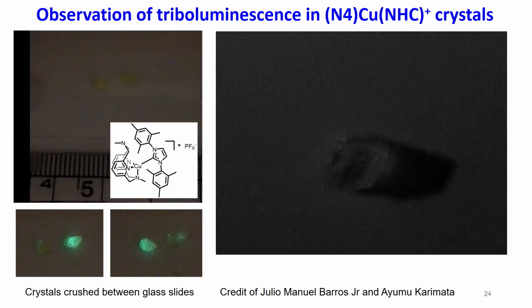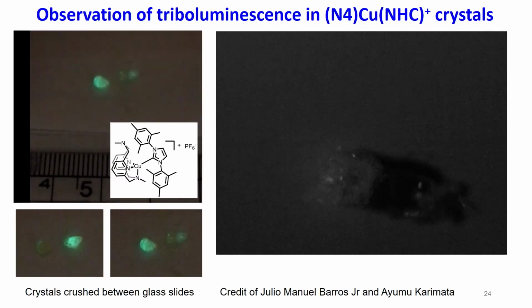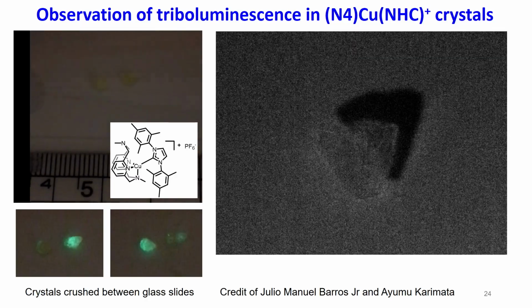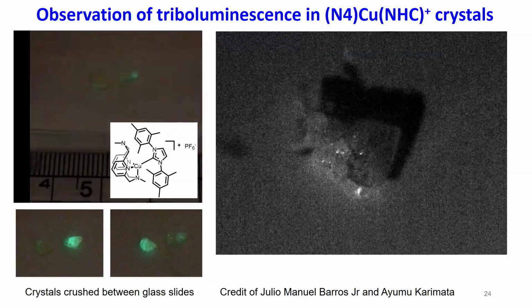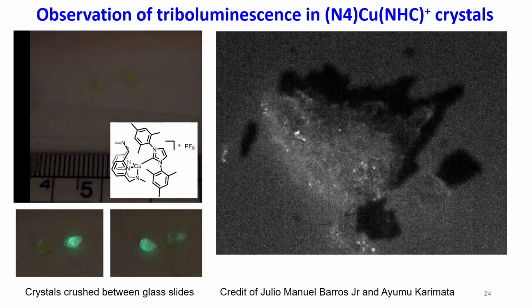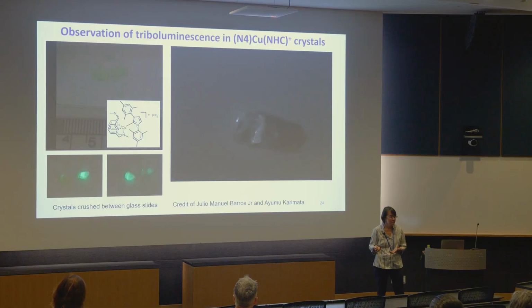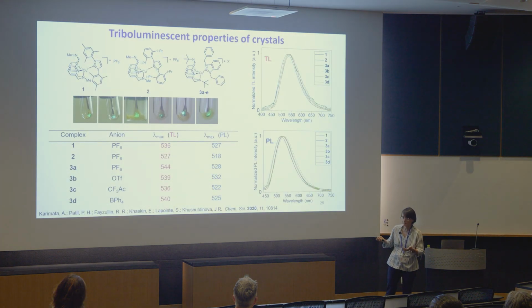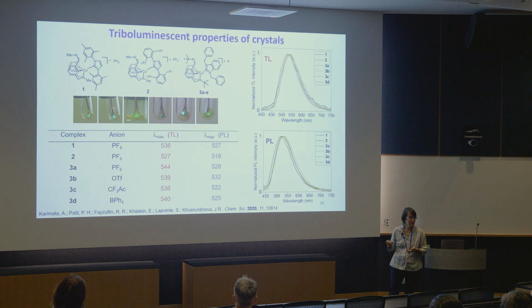You can crush the crystals between two glass plates, and you see this flash of light. Or this is really the same event, but recorded with help of some collaborations with a high-speed camera. So these are triboluminescent compounds, which is a very nice property to study. But the strange thing was that almost all of our complexes were triboluminescent. That's actually unusual because this property is very tricky. It's hard to predict it, and it's very much dependent on the crystal structure. And here we see it in the whole series.